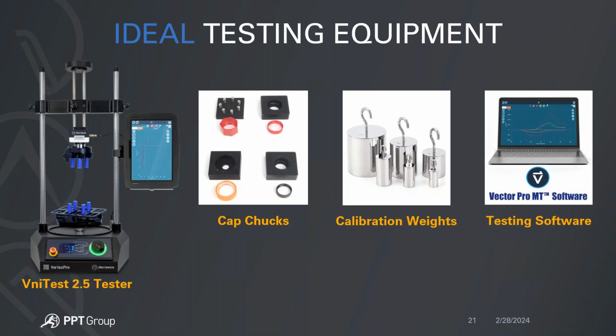And the important part about this is, if you determine that it's 10 pounds of force that's the ideal axial force required. Bear with me just a second while I make this correction. Since it's being recorded, when you get the video on demand, you'll have the accurate information there. So if it's 10 pounds of force that's required to open the caps, then for subsequent testing, if you randomly grabbed a dozen samples and they were not opening with that 10 pounds of axial force, you should be able to identify right away that there's a problem with the release mechanism. So part of this entire process is establishing a standard that's repeatable.